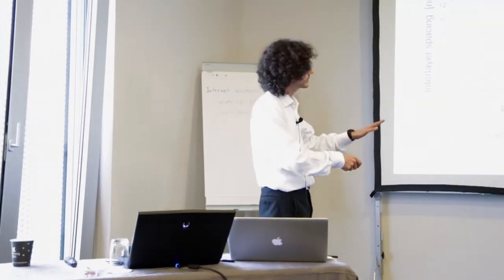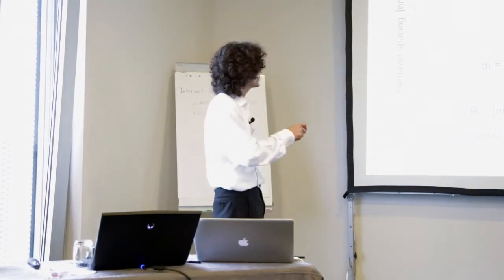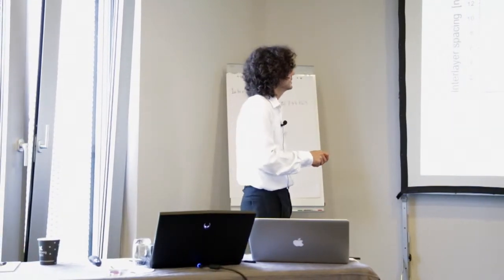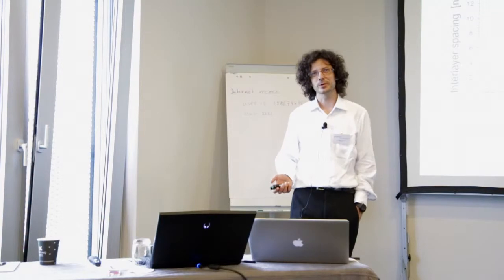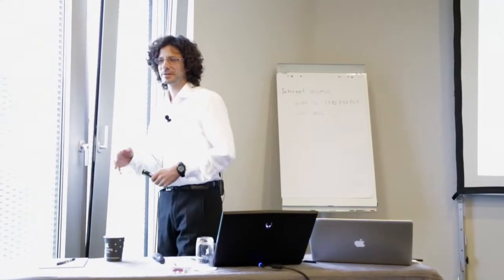So what she did then was to take the calculated layer based on the parameters from this separate publication and plot it versus what she measured as interlayer spacing. And the slope is exactly 2, and the intercept is what you would get without polymer. So it's almost a result too good to be true. The typical thing that one would want to have repeated, but it was done in the last stretch of the PhD.